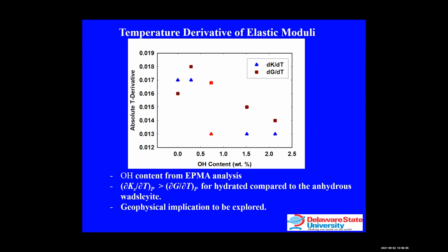This is unusual because most other measurements that we've seen, especially for the anhydrous sample, whether with iron or without iron, show that the effect of temperature on the shear modulus is higher than on the bulk modulus. But for all the wadsleyite samples that we measured, it is showing that temperature affects the bulk modulus more than it affects the shear modulus.